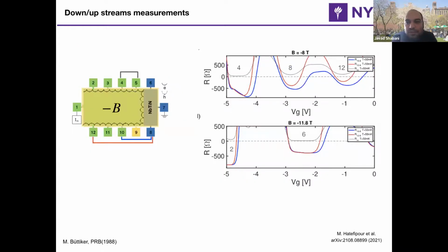So a very straightforward version of this, I guess, is that if I measure, for example, in the left graph, in the schematic, if I compare 10 and 8 versus 12 and 8, right? So basically I'm still measuring across the interface, but then I basically make a longer path across the interface. If I have a very well-defined quantum Hall, it shouldn't matter, right? There is no dissipation across that interface. So let's just focus on the minus 11.8 Tesla. And if you look at the data, the black is the RXX, the normal RXX. It is a relatively well-defined quantum Hall state. And the blue is the shorter path. And you see that basically it likes to quantize at some negative value.